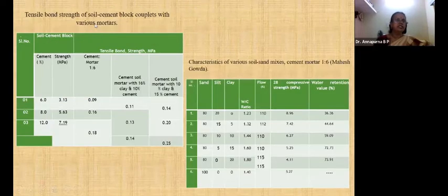Now, tensile bond strength of soil cement block. They have also tested the tensile bond strength for soil cement blocks and the mortars. This is for cement of 6, 8, 12%. The strength achieved for the soil cement block with 6% up to 12% cement is 3.13, 5.63, 7.19. This is the soil cement block.